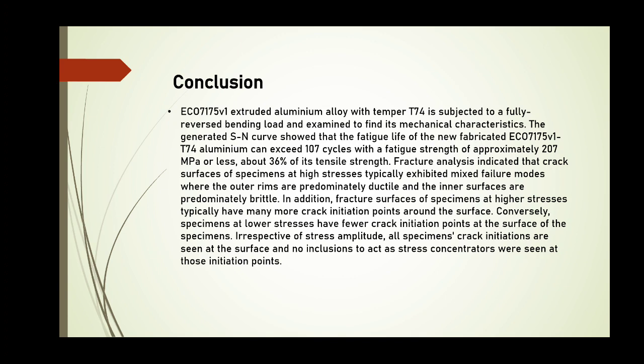In addition, fracture surfaces of specimens at higher stresses typically have many more crack initiation points around the surface. Conversely, specimens at lower stresses have fewer crack initiation points at the surface of the specimens. Irrespective of stress amplitude, all specimens' crack initiation is seen at the surface and no inclusions to act as stress concentrators were seen at those initiation points.